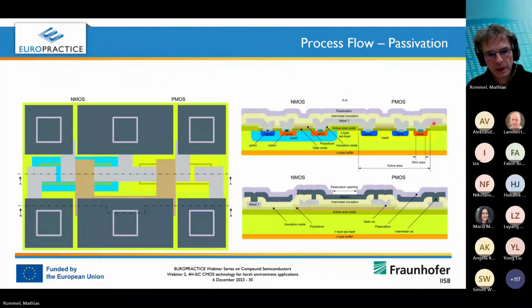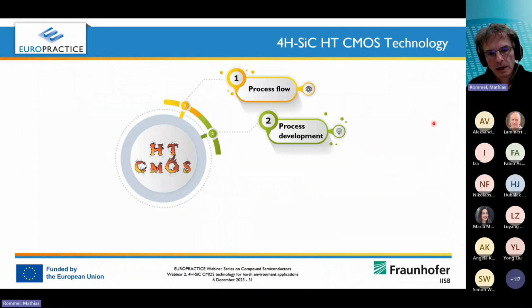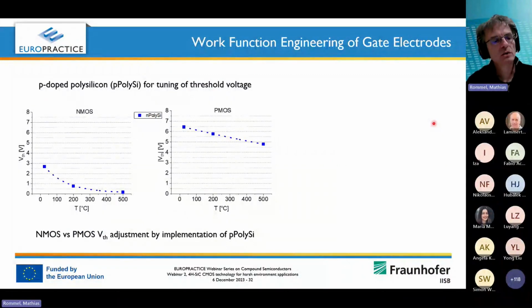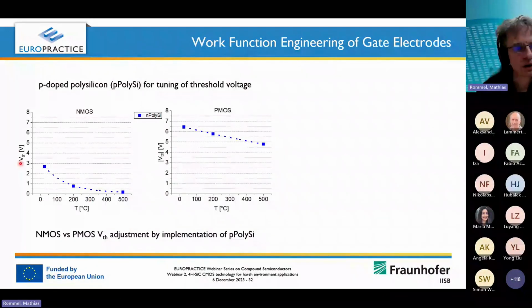Okay, now that's basically the process flow. And a very few words on process development, what we already did and what we aim at. And I start with a picture where we show the threshold voltage dependence on temperature, or the threshold voltage evolution of NMOS transistors and PMOS transistors with temperature. In both cases, we get a smaller threshold voltage with temperature increasing. And as you can see here, for example, for the NMOS at 500 degrees, you get relatively small threshold voltages.